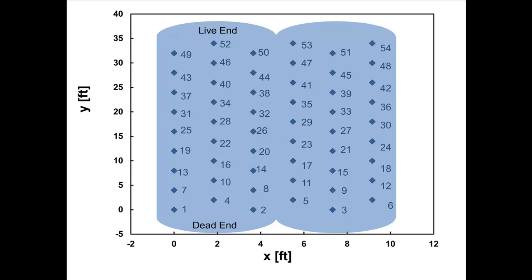Prior to testing the cylinder, an attenuation study was performed to show that the high-frequency component of waveforms could propagate sufficient distance in specific directions without attenuating below the noise floor using the particular broadband transducers that were to be employed during the pressurization of the cylinder. The attenuation analysis was presented to the independent authority, the method accepted, and the increased sensor spacing was used.